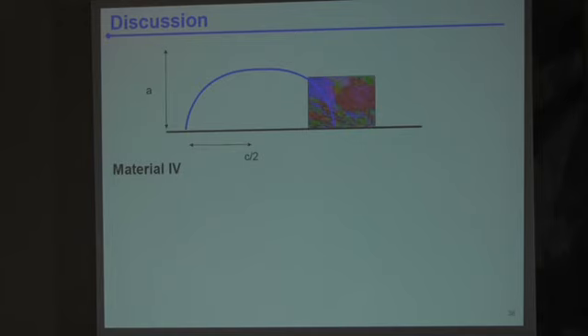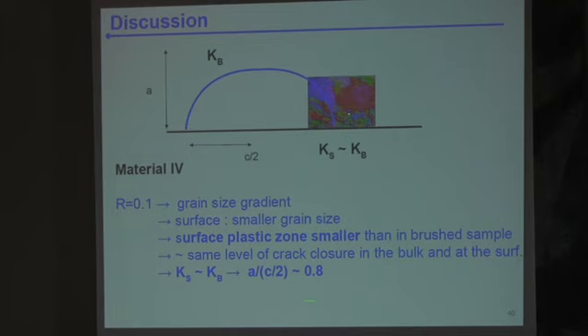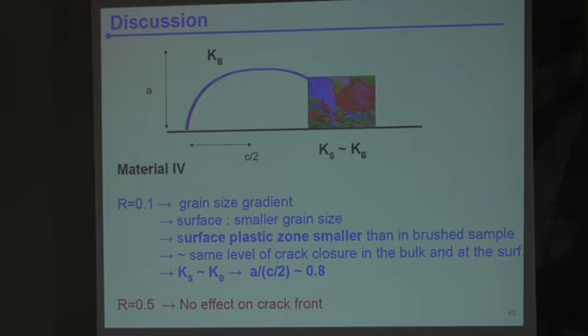Now, why is it so different for material number 4? Well, you might remember that in this material, you have a microstructure gradient. You have smaller grains at the surface. This is at the scale here. So, more or less on maybe 20 microns, you get smaller grains. And we believe that they are quite effective in increasing the local hardness below the surface. And if you have a higher hardness, higher yield stress, then you have a smaller plastic zone probably at the surface. And a smaller plastic zone, if you assume that the closure that is there is due to plasticity effect, then the closure effect should maybe be smaller or reduced at least. Okay? So in that case, going from 0.1 to 0.5 should make no big difference, which is indeed what we see.